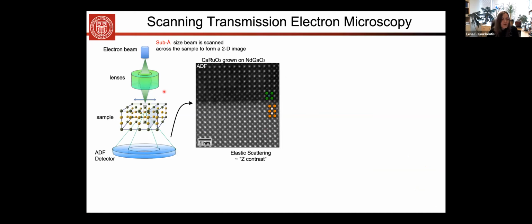So you heard about TEM, where you have a parallel beam that illuminates the sample. Here, this is a little bit different. Here we focus a very, very small electron beam onto the sample. The electron then interacts with the sample, and you can record a number of different signals. The most straightforward is to just look at the elastically scattered signal, and that produces a two-dimensional image when you raster the beam across your specimen.